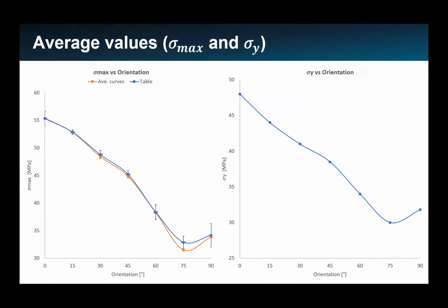As expected, the maximum strength was obtained for the specimen printed at 0 degrees. There were some errors performing these tests because, for some reason, the specimen printed at 90 degrees is stronger than the one printed at 75 degrees. So we need to do some corrections on these tests, but this is just to show you the data we are obtaining.